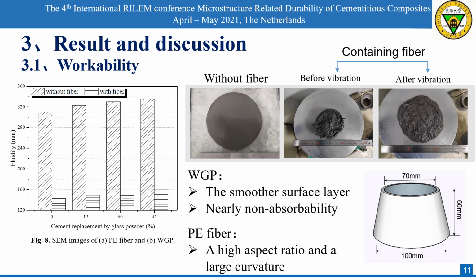Figure 8 shows the fluidity of fresh UHS-HDCC mixtures with fiber or without fiber. It is important to note that the added WGP has a positive effect on the fluidity of fresh UHS-HDCC. However, PE fiber has a high aspect ratio and a large curvature, which has a serious impact on the fluidity of the matrix. The damage to fluidity is inevitable to meet the high ductility of the ultra-high strength matrix. However, the fluidity of the fresh fiber mixture with WGP is slightly improved. The change may be attributed to the smoother surface layer and nearly non-absorbability of WGP.